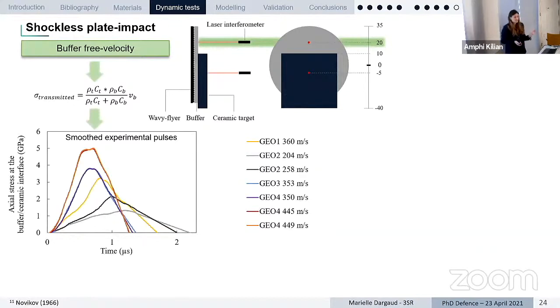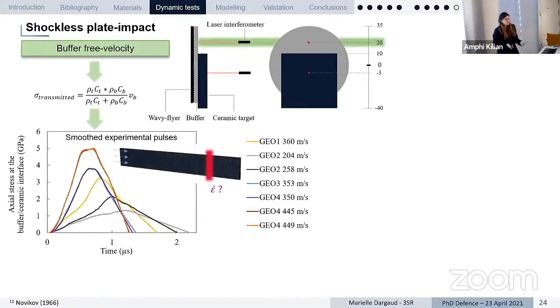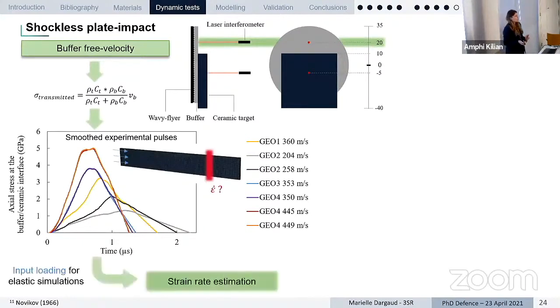And you can see here for all the different configurations that we've used that we managed to reach a triangle pulse. So we see that it is working. By playing on the different shapes and configurations, we can change the shape of this transferred stress. Then we've used this experimental pulse as an input for numerical simulations to evaluate what was the strain rate generated upon impact in the failure zone. To do this, we've done elastoplastic simulations, and this allowed us to evaluate the strain rate.